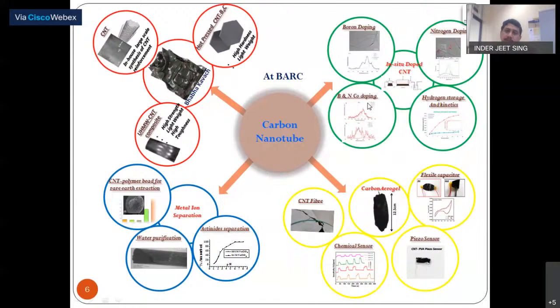Also, we are working on the doping of carbon nanotube with heteroatoms like boron, nitrogen, and co-doping with boron and nitrogen for hydrogen storage. We are finding out their kinetics. Then we have used carbon nanotubes for metal ion separation, like carbon nanotube polymer beads for rare earth extraction, for actinide separation, for water purification.